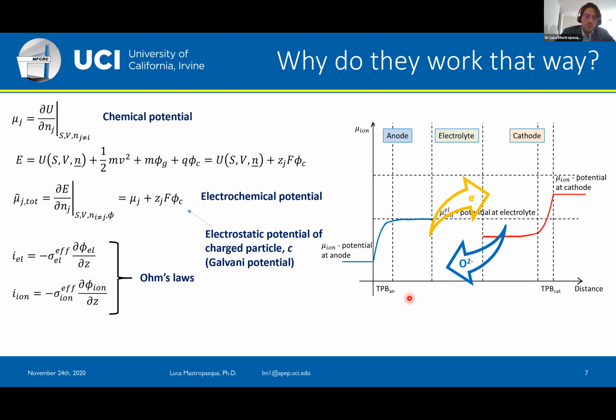So I've qualitatively sketched the gradient of the ionic potential in a typical fuel cell condition, where we have the ionic potential that is greater at the cathode side and lower at the anode side. And this creates a flux of oxygen ions from the cathode to the anode. And in order to maintain the charge neutrality of the system, we must have an equal amount of electrons flowing in the opposite direction. And this is where the electrons flow into the external electric circuit and produce useful work.